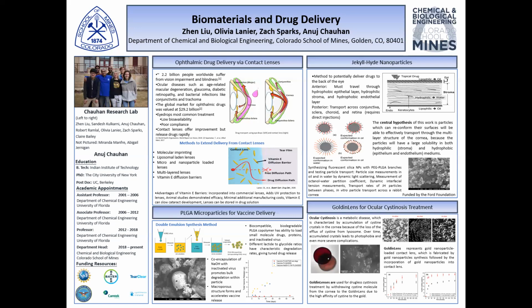In this particular particle sample, there was a co-encapsulation of sodium hydroxide. With the encapsulation of sodium hydroxide, this promoted bulk degradation from within the particle, giving a macroporous structure, which in turn accelerates the vaccine release.